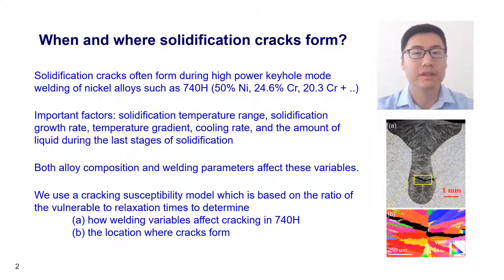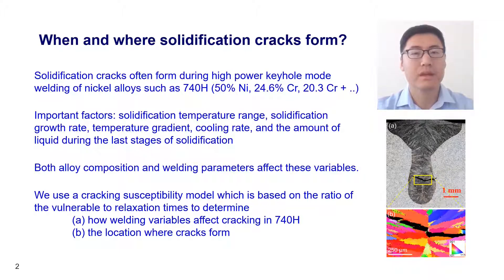Solidification cracking can occur at the keyhole finger during high-power keyhole mode laser welding of nickel alloys. Many factors are responsible for cracking. For example, a large solidification temperature range will result in a large liquid-solid two-phase region, which is weak and susceptible to solidification cracking. Solidification parameters such as temperature gradient and cooling rate can significantly affect the morphology of the solidified alloy and affect cracking. The amount of liquid during the last stage of solidification determines whether cracking can be healed by feeding liquid from the solidifying fusion zone. All of these factors depend on alloy composition and welding parameters.